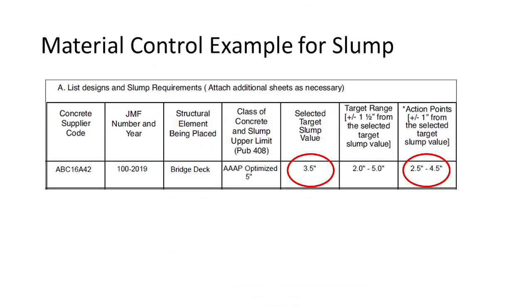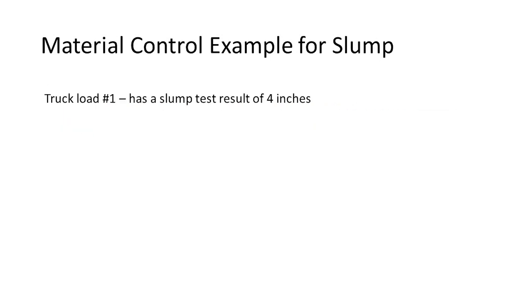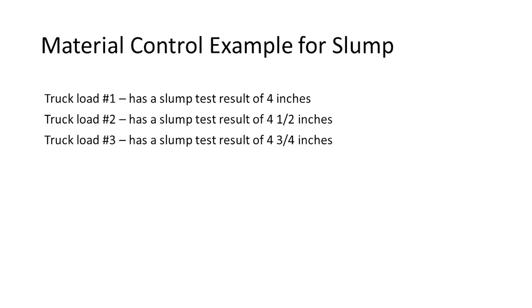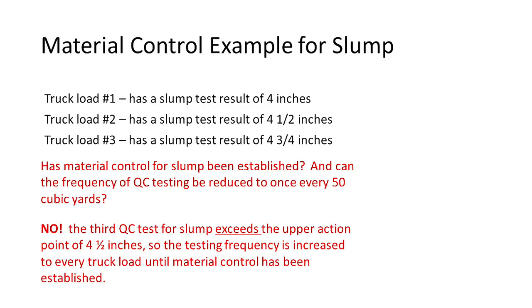The selected target slump noted above in this QC plan is 3.5 inches. Take note of the required action points. Truckload number 1 has a slump test result of 4 inches. Truckload number 2 has a slump test result of 4.5 inches. Truckload number 3 has a slump test result of 4 3/4 inches. Has material control been established, and can the frequency of testing be reduced to once every 50 cubic yards? No. The third QC test exceeds the upper action point of 4.5 inches, so the QC testing frequency will be increased to every truckload until material control has been established.